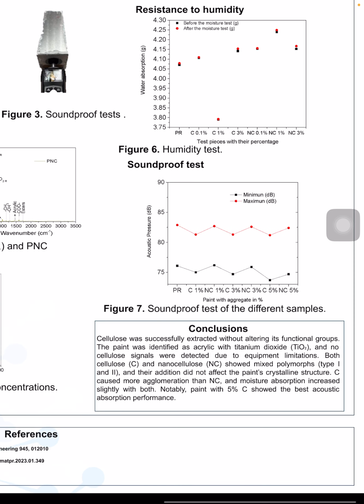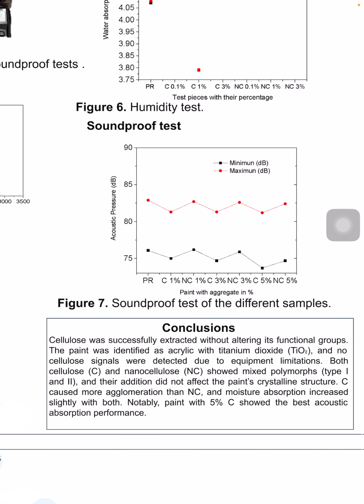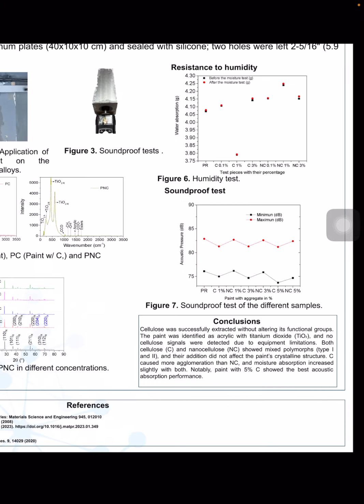So, in conclusion, cellulose was successfully extracted without altering its functional groups. The paint was identified as acrylic with titanium dioxide, and no cellulose signals were detected due to equipment limitations. Both cellulose and nanocellulose show mixed polymorph, type 1 and type 2, and their addition did not affect the paint crystalline structure. C caused more agglomeration than NC, and moisture absorption increased slightly with both. Notably, paint with 5% of C showed the best acoustic absorption performance.